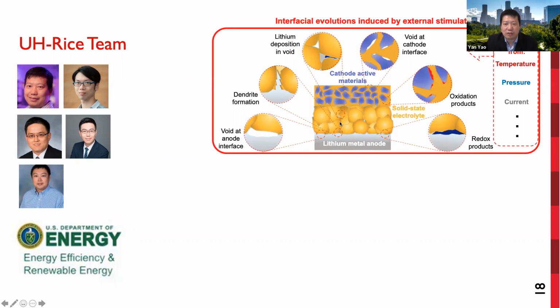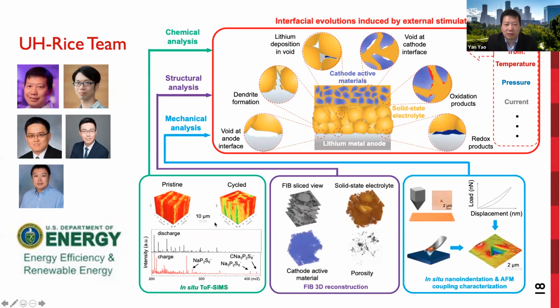So the resistance increase may be attributed to electrolyte decomposition at the interface and void formation, which happens at both the cathode-electrolyte and anode-electrolyte interfaces. So we decided to approach this complex origin of battery failure using not only one technique, but a combination of 3 techniques as a tool set, including the